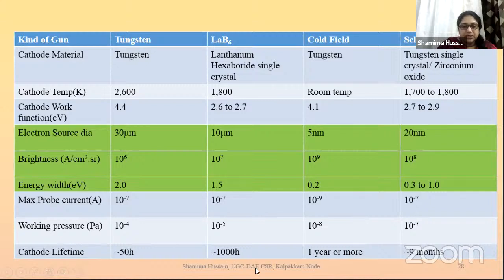Now, even you see the lifetime that I was mentioning here: 50 hours for tungsten, which is close to 3 days. Lanthanum hexaboride almost 1,000 hours. It's higher, but not that high. Schottky had 9 months because in between there was a downtime also when we were cleaning the diode surface. And FEG, 1 year or more is what is mentioned. I myself personally have used it for more than 2 years. So it's quite sturdy that way.